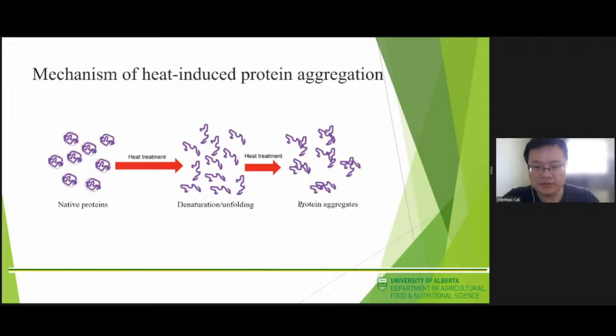Using protein aggregates as a pretexturization approach has been applied to increase the texture of dairy protein-based matrices. Gels formed from the aggregates may possess improved strength due to the reinforcing effect of aggregate fillers. Also, the heating can expose the active groups on the aggregate surface to improve their interactions with each other to strengthen the gel networks. In such systems, the aggregate structure, size, charge, morphology, and active group directly determine the gel mechanical properties.